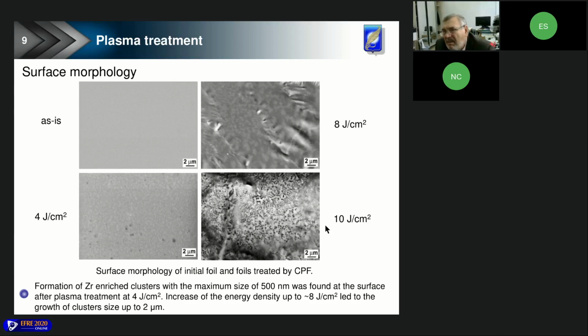The further increase of the energy density resulted in cluster size increase up to 2 micrometers. This treatment regime corresponded to appearance of crystalline phases of alpha zirconium, zirconium titanium solid solution, and nickel. At the same time, energy dispersive X-ray analysis didn't reveal changes in the homogeneous distribution of elements, just a bit. Besides that, formation of small dendrites and a discontinuous surface film was found after increase of the energy up to 10 joule per square centimeter. These effects can be seen more clearly on the next slide.